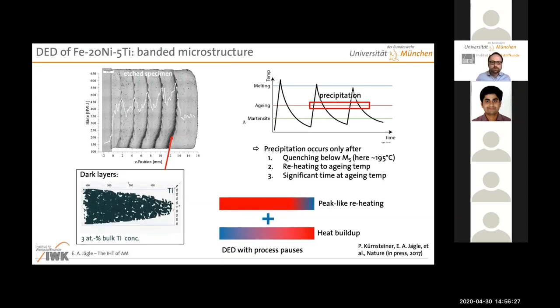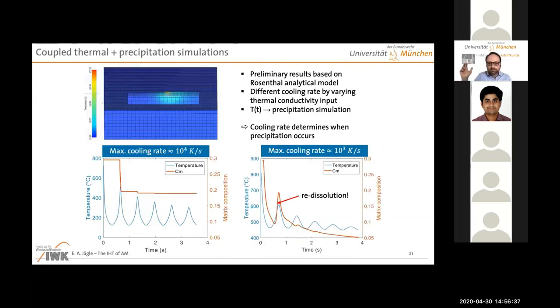Because there are already so many people working on build simulations for completely different reasons. So I think also commercially, if you look at Netfabb and from Siemens and plenty of other people, you more and more routinely simulate the thermals of your process before you press play on your printer. You do this for different reasons. You do this, of course, for thermal warping, for residual stresses.